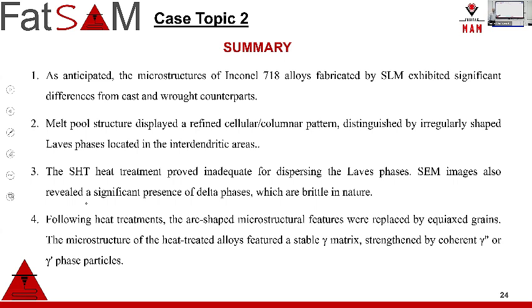So still, additive manufacturing has issues with them. Why? I would like to stay just 1 minute more in this second results. The biggest problem in additive manufacturing, we cannot use this material composition as we use in casting and wrought processing. So we have to make, especially in terms of face-centered cubic materials, like superalloys, nickel-based superalloys, them weldable. So what we are doing, we increase the chrome ratio a little bit, decrease the carbon a little bit, which can be seen.